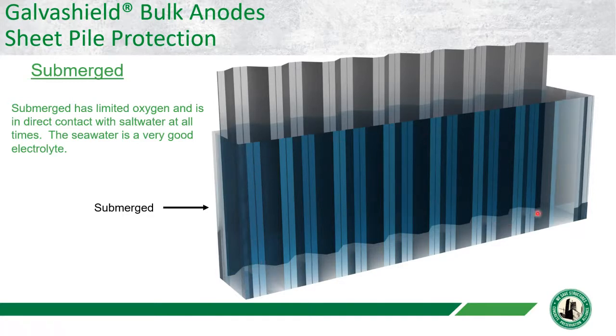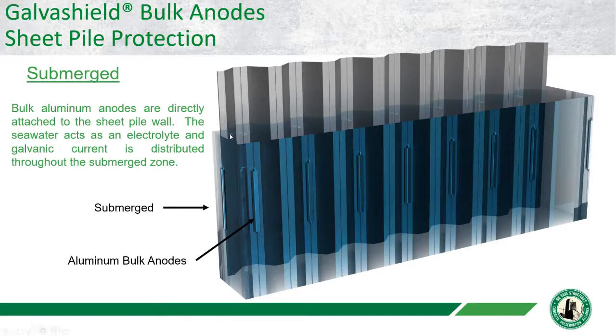But because of the seawater, it actually makes it very, very easy to provide cathodic protection. So we will end up using the seawater to our benefit to help provide cathodic protection. Seawater is also a really good electrolyte, so that's also pretty good. So what we'll do for the submerged section is we can just take some bulk aluminum anodes and weld them. These aluminum anodes are electrically connected to the sheet pile wall. And as they're connected and submerged in this salt water, they're going to oxidize, basically release electrons, and it's going to protect everything within this submerged zone.